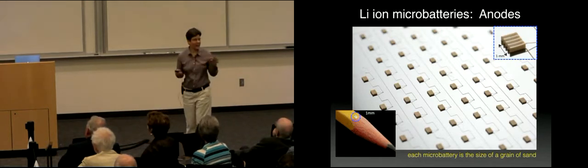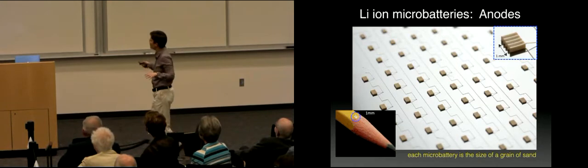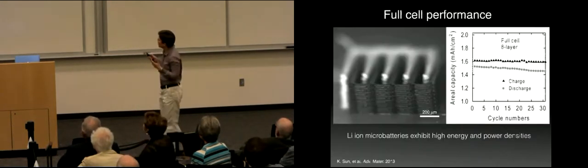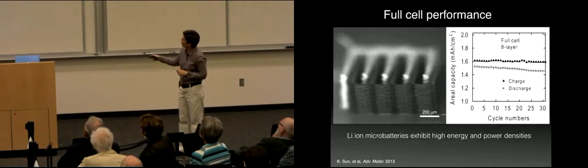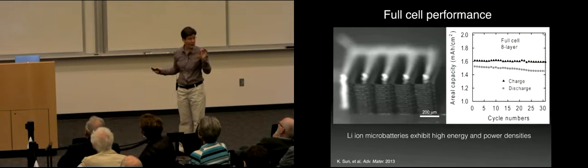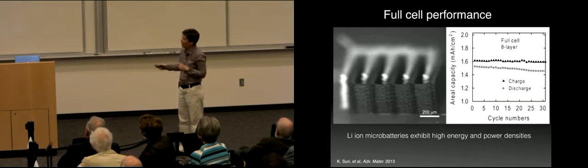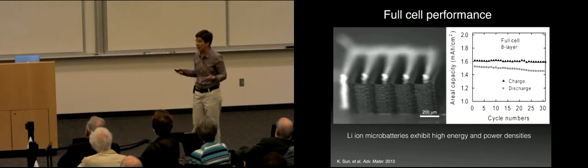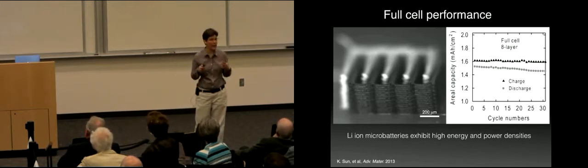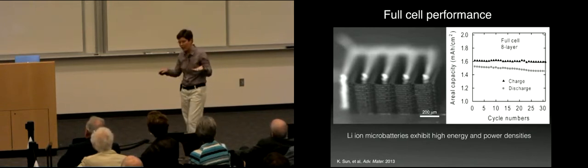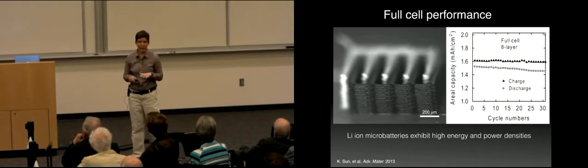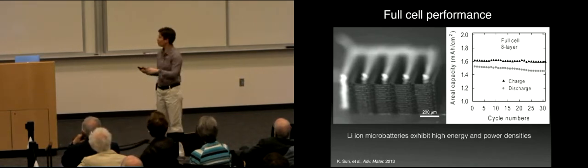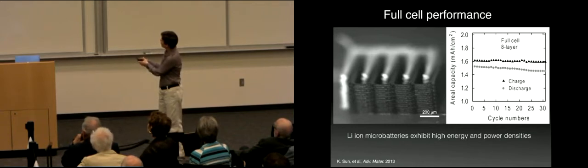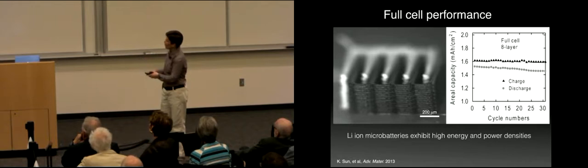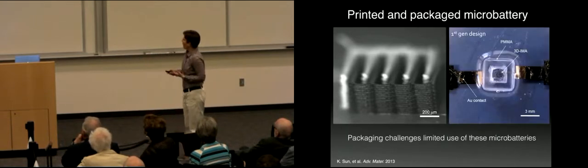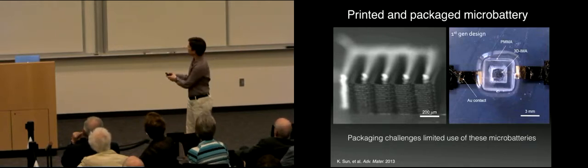Okay. Now, having said that, it doesn't have a lot of energy density or energy capacity, right? Because it's really small. But it works. So the white is the anode, the dark features are the lithium iron phosphate. That's interdigitated. And if we just do a number of charge-discharge cycles, this is 25 cycles, we can measure the energy capacity per area. For micro batteries, area is really the name of the game. They're normally made by thin film deposition. Now we're able to go out of plane, obviously, through a number of layers. And this is what the battery performance looks like, charge-discharge. Pretty stable, it works. Then we packaged it. Well, generation one pretty much was a disaster.